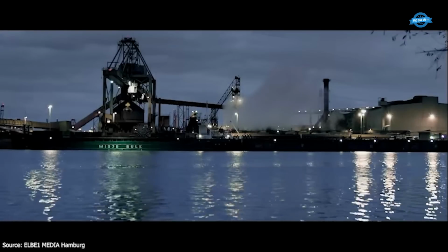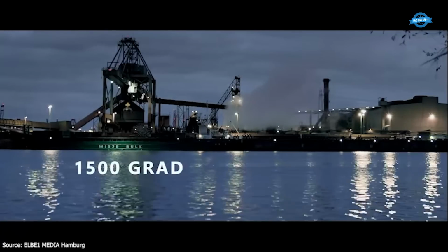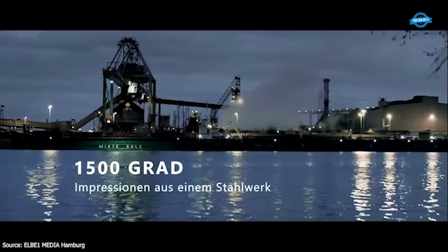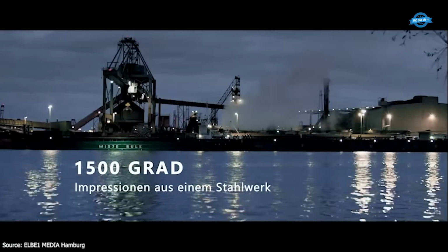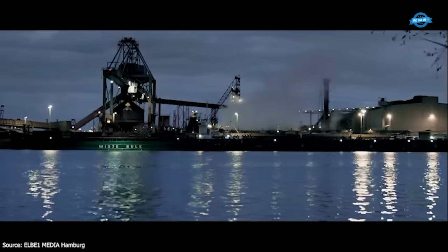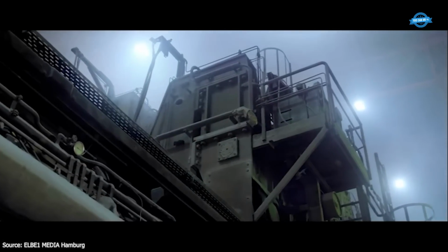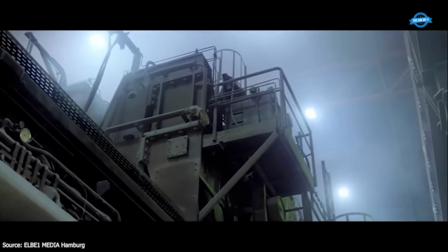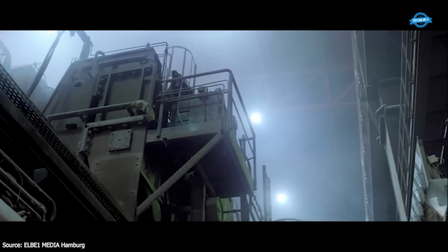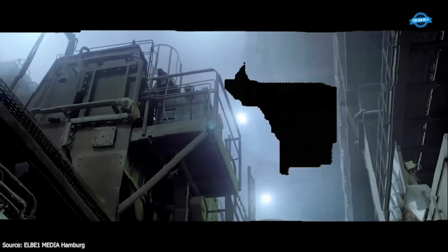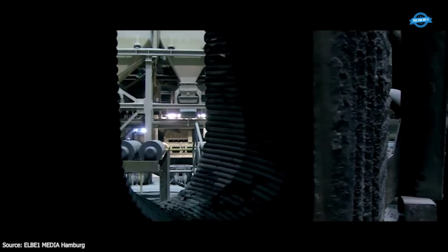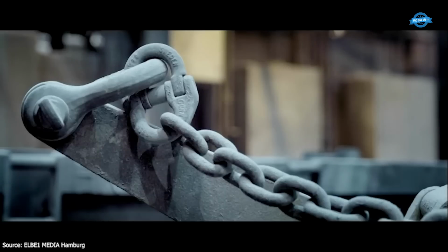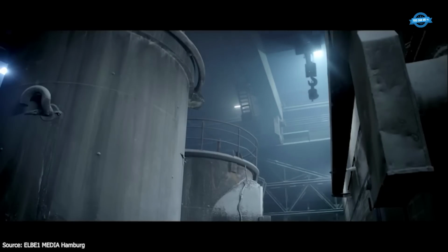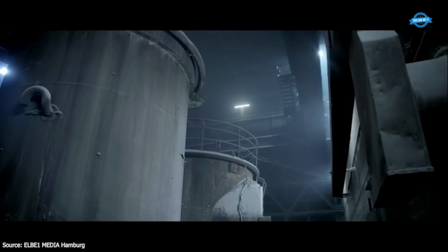ArcelorMittal Hamburg operates a highly advanced and sustainable steel production process, combining direct reduced iron (DRI) technology with an electric arc furnace (EAF). Production begins with iron ore pellets, which undergo direct reduction at approximately 800 degrees Celsius using natural gas. This process converts iron ore into sponge iron (DRI) with a metallization degree of 95% and a carbon content of 2.3%, without the need to melt the ore, significantly reducing energy consumption.